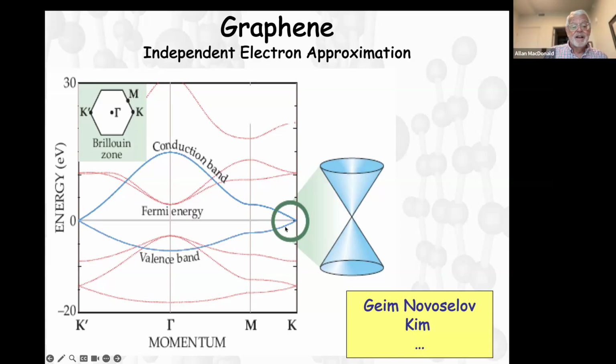The most important property of graphene is that it's a honeycomb lattice of carbon atoms, and the splitting between the pi bands comes from hybridization between the different sublattices, and that hybridization vanishes by symmetry at the corners of the Brillouin zone.